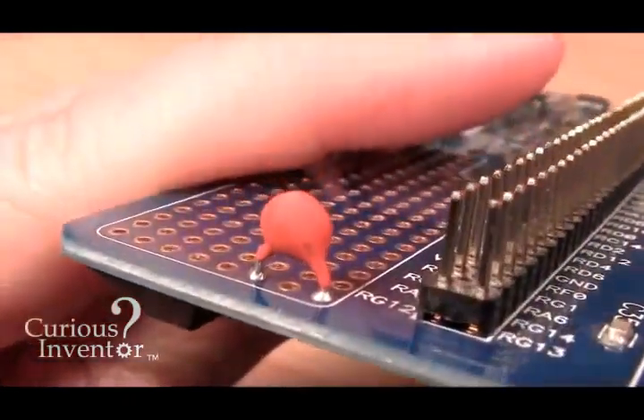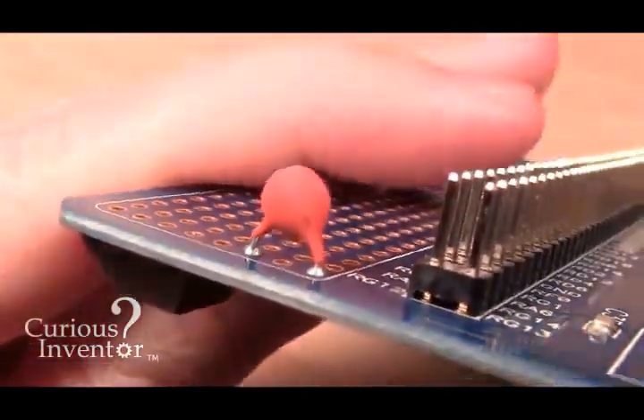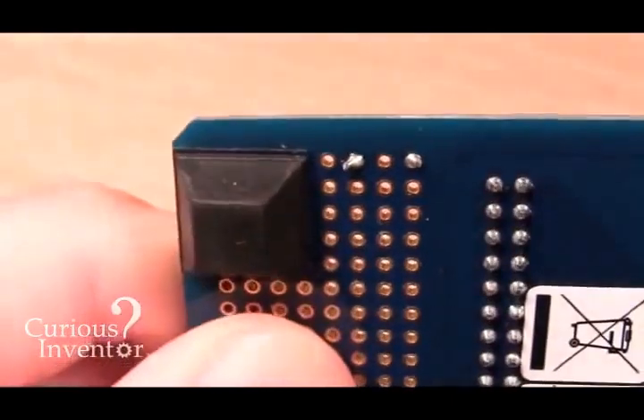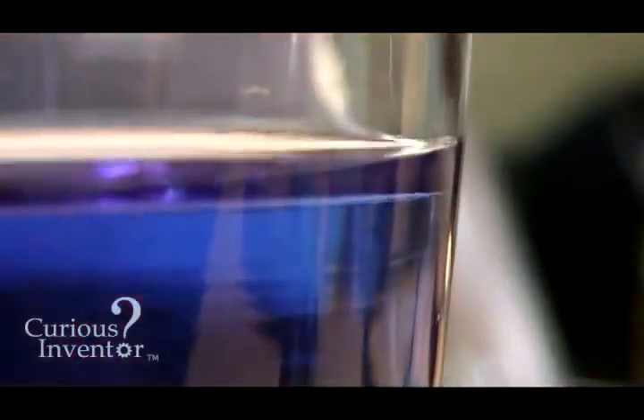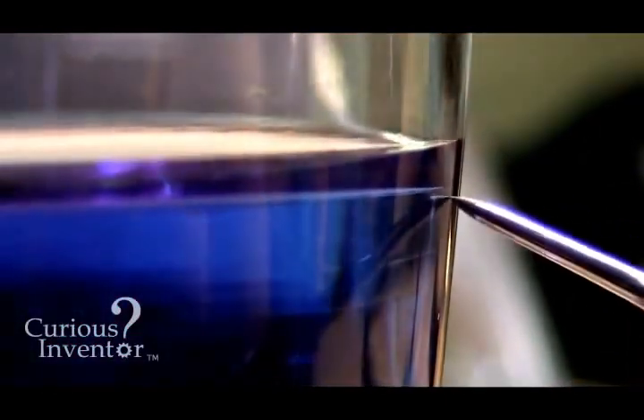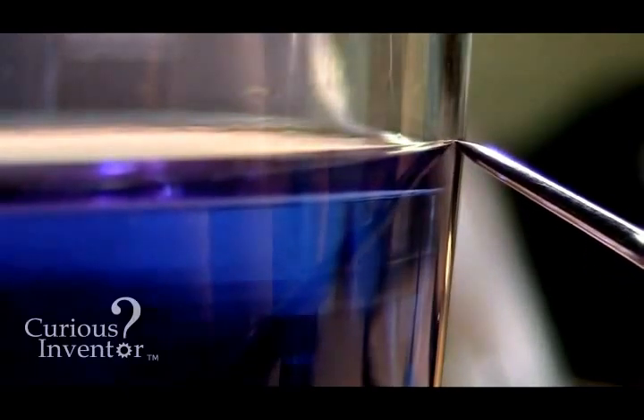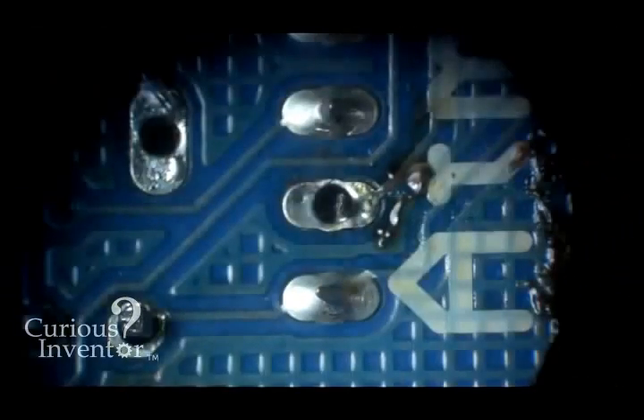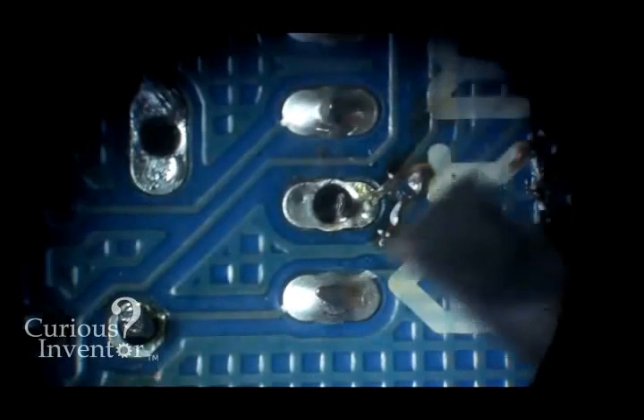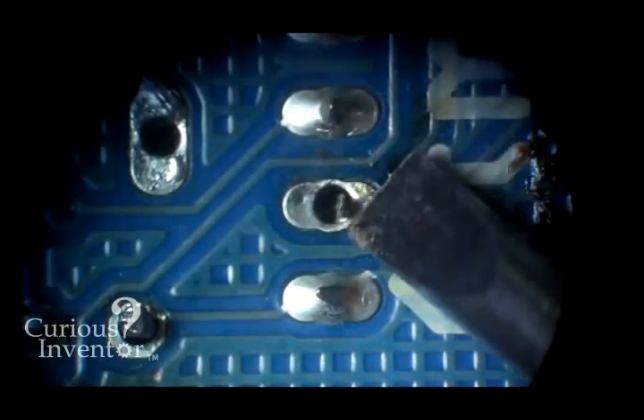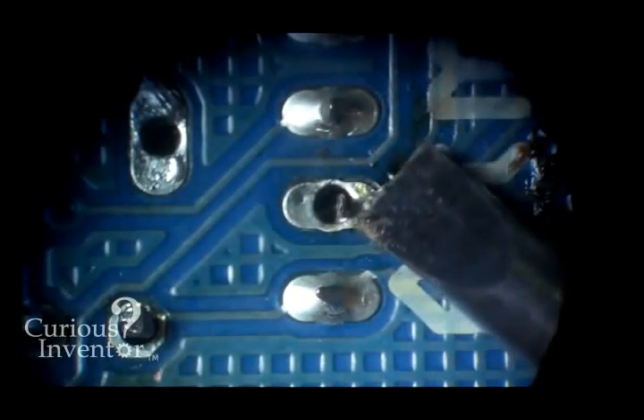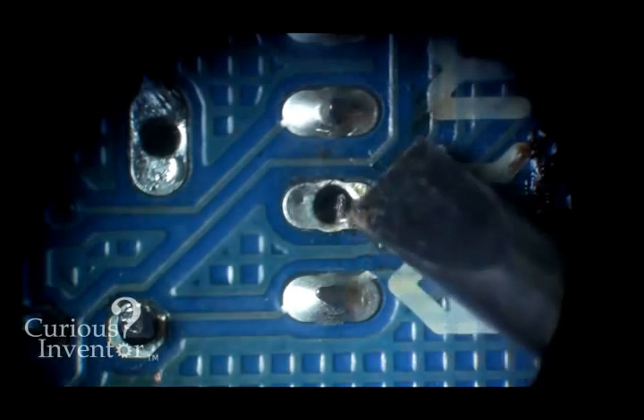Boards like these are much more difficult because you need to remove solder from both sides and inside the metal tube also. The same capillary forces that cause water to climb the walls of a glass also act to hold solder in the hole. Here I've used wick on this plated through hole joint, and if we look up close, there's still solder remaining between the pin and the wall of the tube. Since this part has many pins, we need to make sure each one is completely free before trying to pull the whole part out to avoid breaking a pin or a hole.